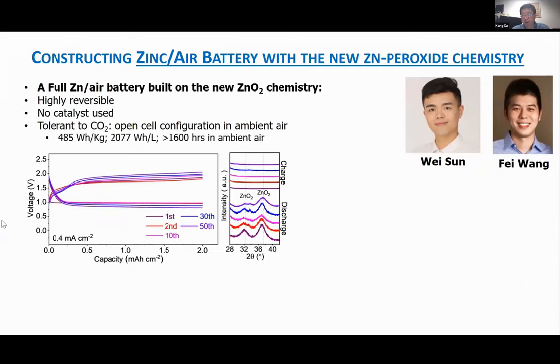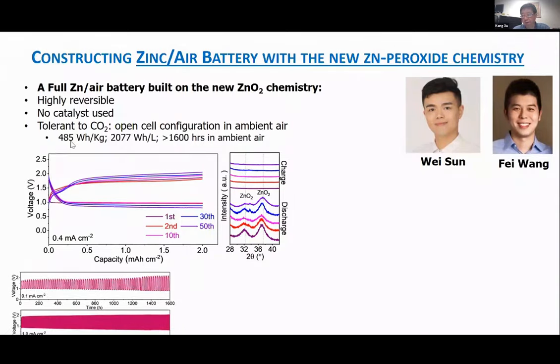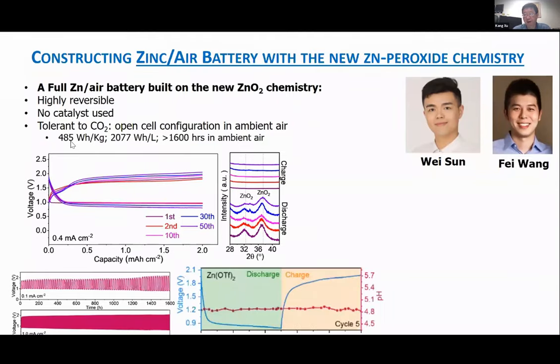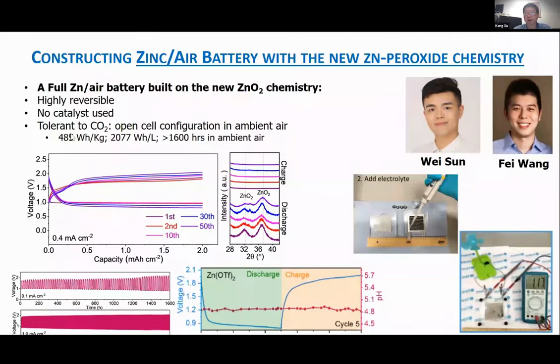There's no pH change. It's extremely reversible, and the cell we can assemble into a pouch cell gives us 485 watt hour per kilogram, when we count everything: the electrolyte, anode, cathode, and the cell packaging. We found that it's very reversible. We did an in situ XRD, which proves that it's only zinc peroxide which is forming. And the anode side here is still not the most recent work that we achieved.